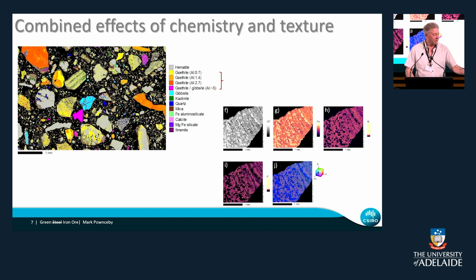So if you look at the top left image, that's a typical Australian iron ore. The hematite is in the grey. The goethite is in various types of orange. And you can see there are some particles there. There's a hematite particle mixed with a bit of quartz. There's hematite mixed with kaolinite. You can also see that the goethite itself is really inhomogeneous texturally. It's got different levels of alumina in there, ranging from about 0.7 up to about 5%. So this is the complexity that we're dealing with when we're talking about beneficiation of iron ores.